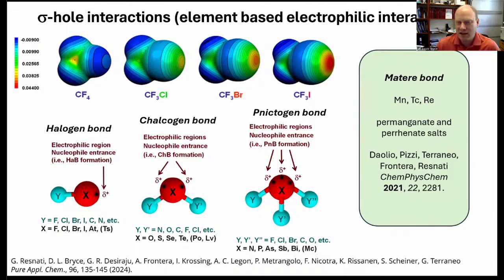So despite the fact that this heavy iodine atom has a lot of electrons around it, the CF3 electron withdrawing group creates this so-called sigma hole, which can accept electrons and form these non-covalent bonds. And there are some analogous classes of interactions, for example, the chalcogen bond, the pnictogen bond, or you can see below here the formation of 2 or 3 sigma holes in these cases, and these can interact with electron donors to form cocrystals and that sort of thing in the solid state.